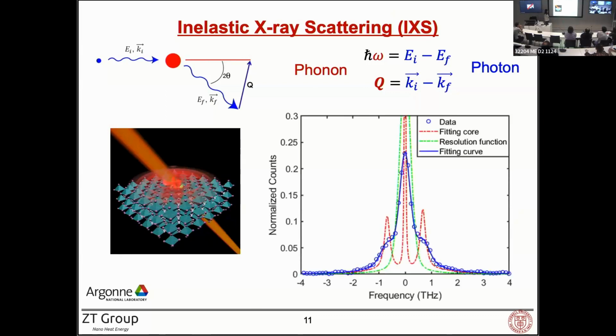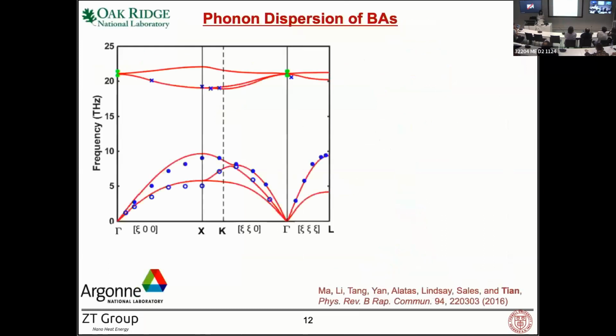This is how a typical energy scan looks. The circles are from our measured data. In the center, we have the elastic peak, and on the two sides, we have the phonon annihilation and the phonon creation. From these peak positions, we get the phonon frequency, and the inverse of the peak width gives us the phonon lifetime. So our key results are summarized here.